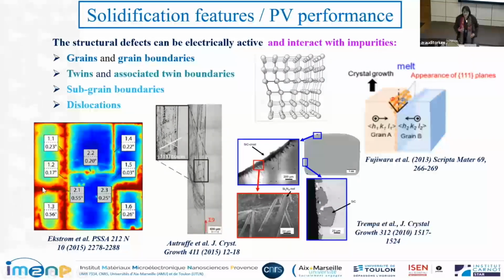And on top of this, you have impurities that come from your initial silicon feedstock or your furnace environment and the crucibles. And the impurities will create specific defects, as you will see in the following, in my case study on carbon contamination, and also segregate at the level of the structural defects.